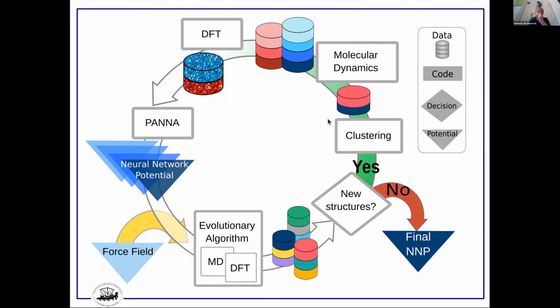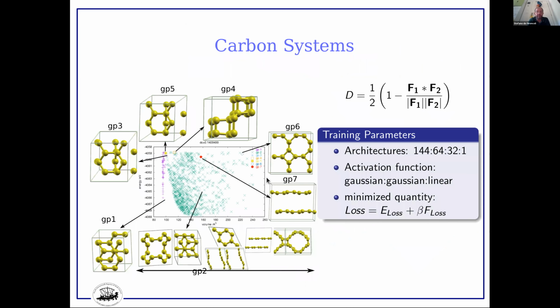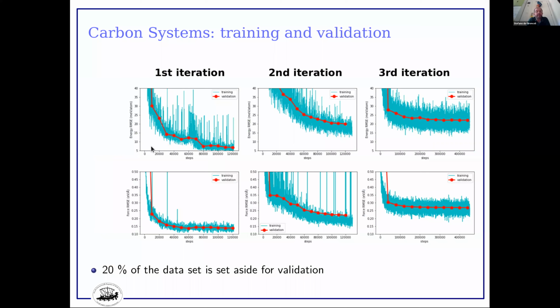And so for carbon, we started with some reactive force field, and we found a number of different structures. We did the DFT calculation associated to that. We trained, and basically we repeated this for a number of cycles. And what you can see is the error per atom. So the three top panels are the error in the energy, in millielectron volt per atom. And then the bottom three panels are in electron volt per angstrom. That is the error on the forces.